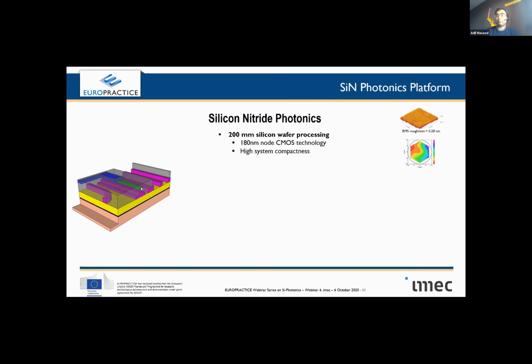Since it's wafer level processing, one fabrication lot typically contains 20 or 2 dozen wafers, and every wafer can have up to, depending on how big your die size is, 60, 70 dies. So that means that even one fabrication run can yield you hundreds of dies, not really for device fabrication, but at least for measurement. So you can really control your process. You can statistically monitor it and learn from it. And that is one big benefit of using CMOS technology at wafer level, that you get a lot of data back. As you can see, I'm just giving one example, the RMS surface roughness of silicon nitride deposition. It shows a 0.28 nanometer variation, and the diagram below shows how it's spread over the wafer.